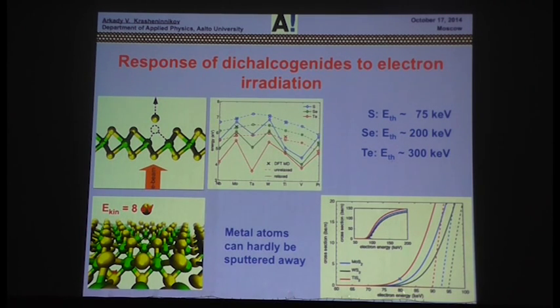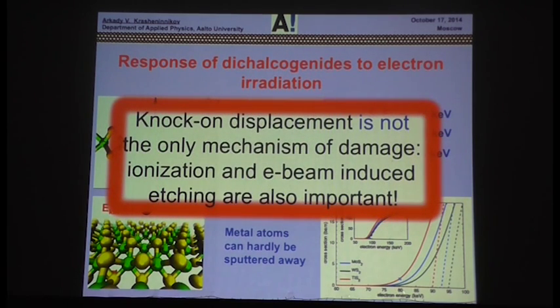Moreover, using the so-called McKinley-Feshbach formalism, you can calculate the displacement rate as a function of electron energy and compare with the experiment. Basically, the blue curve is for molybdenum disulfide. These are the calculations, and this is the experimental point, clearly above the calculations. This means that in addition to knock-on damage, other channels work, basically ionization, electron beam-induced excitations, and possibly etching. It's still not clear to me what the dominant mechanism is there.